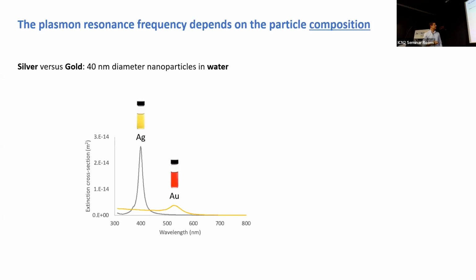So if we take silver versus gold, this is 40 nanometer silver nanoparticle in water, and they have an extinction cross-section with a peak around 400 nanometers, and gold has a smaller extinction cross-section with a peak around 530. And actually, silver looks yellow. So why is a suspension of silver nanoparticle in water yellow?